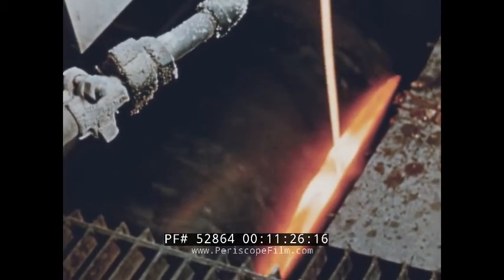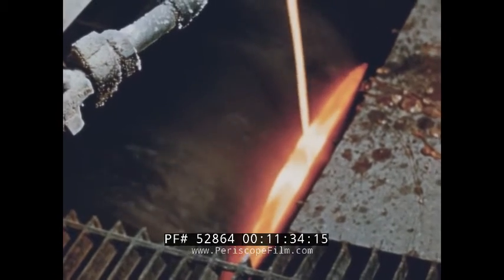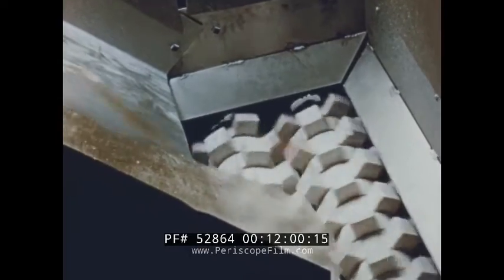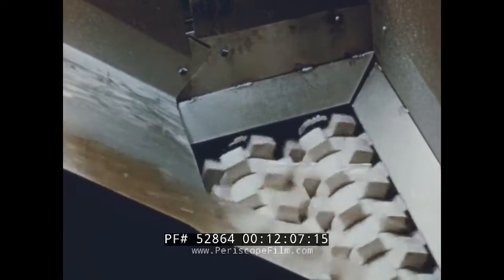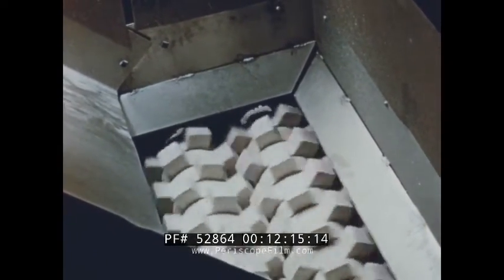The molten glass then falls between two water-cooled rollers, which squeeze it into a thin sheet that passes through an opening in the floor and down a chute to be crushed. This thin sheet is about 30 thousandths of an inch thick, and its width is controlled by the rate of flow of the liquid glass over the lip of the smelter. The sheet of compounded glass rolls into special crushers made of ceramic material that is steel-hard. Because they are of ceramic material, particles from the crushers cannot contaminate the glass. Old-fashioned crushers were made of metal, and iron particles would frequently come off into the glass and have to be eliminated before packing.